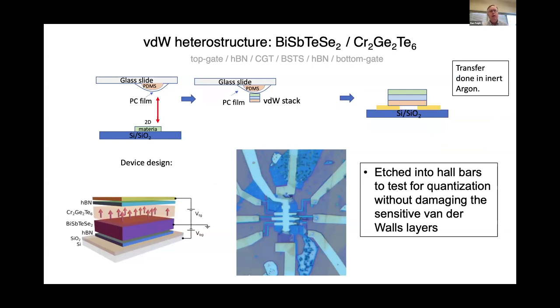Okay. So the techniques we use to make the devices are now fairly standard techniques within the 2D community for picking up individual layers and stacking them. What's a little bit different in our devices is that the trick that allows our work to proceed is that we've developed etching protocols to be able to etch through and make well-quantized Hall bars to actually make quantitative measurements of the resistance and Hall conductivity without damaging the sensitive van der Waals layers. So that's what's new that hasn't been done before.